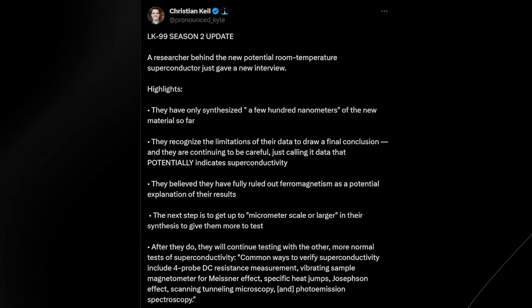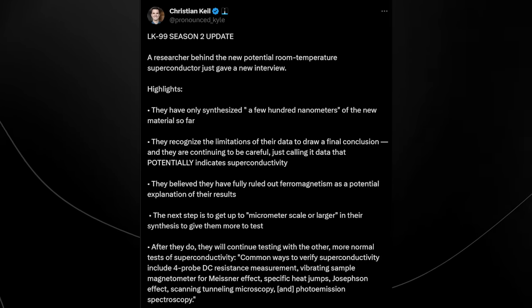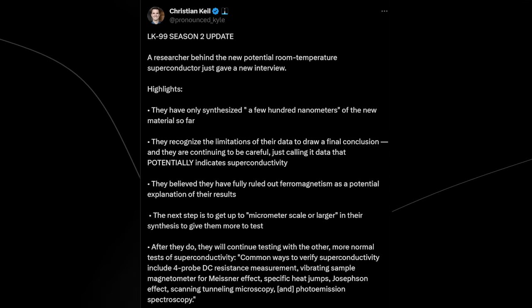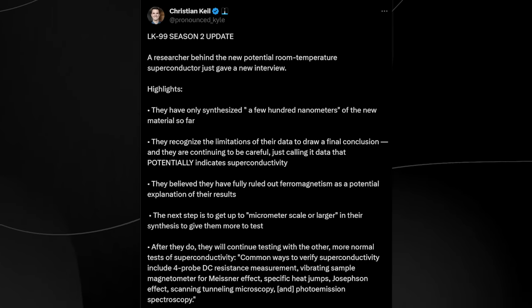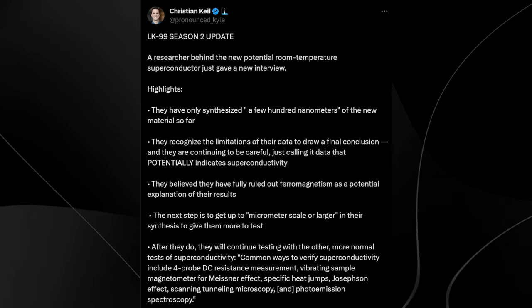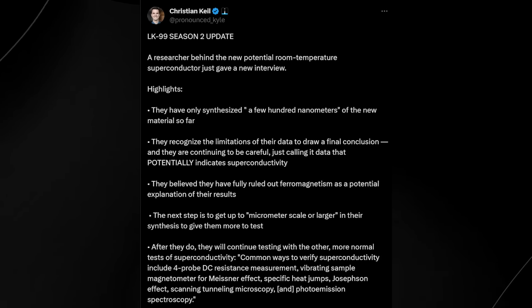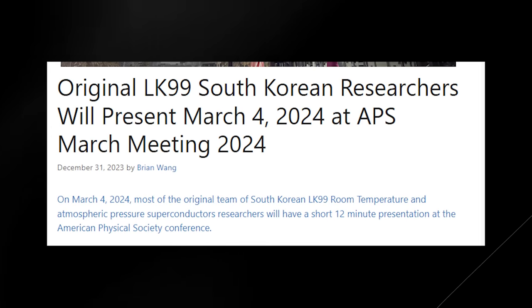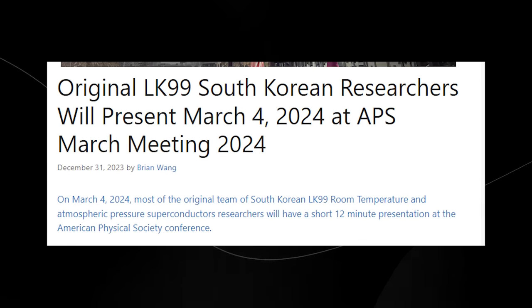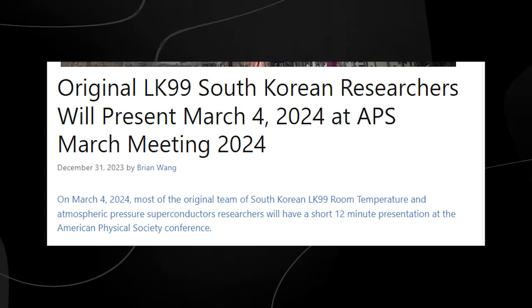Common ways to verify superconductivity include 4-probe DC resistance measurement, vibrating sample magnetometer for Meissner effect, specific heat jumps, Josephson effect, scanning tunneling microscopy, and photoemission spectroscopy. So what's next for LK-99? Well, the original LK-99 South Korean researchers will present March 4, 2024 at APS March Meeting 2024.